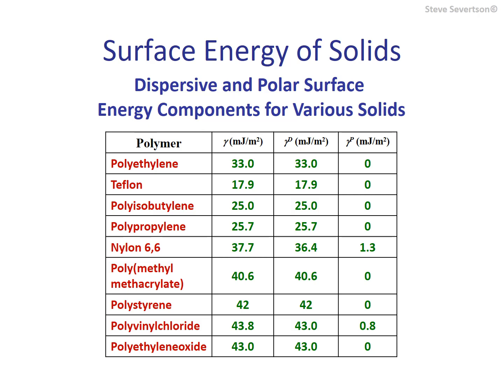This table shows estimates of surface energy values for a handful of polymers. These surface energy values were estimated from contact angle measurements made with probe organic liquids on the surfaces of the polymers, and then the data was interpreted using either the Owens-Wendt plot or the FOWKES approach. The table lists the total surface energy for these polymeric materials, split between dispersive and polar contributions.